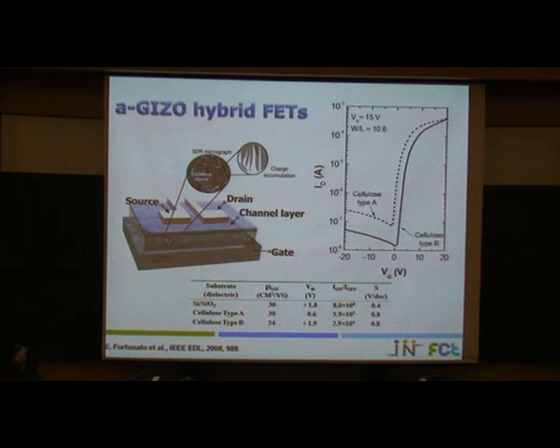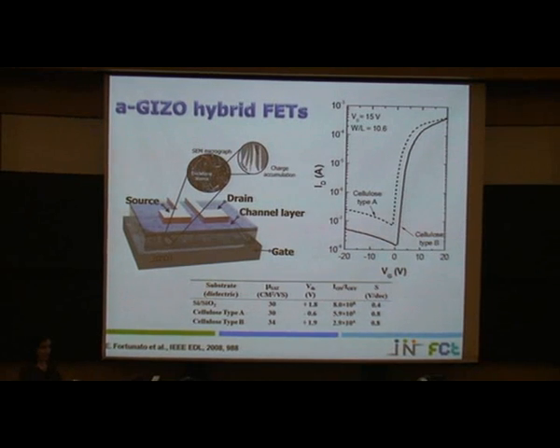And more recently, just to finish the talk, since we are working at room temperature, we are not limited by the type of substrate we are using. We thought to substitute our dielectric film, our silicon oxide or aluminum oxide, with a simple sheet of paper, because you know paper is insulating. And instead of growing all the layers and producing the device with a substrate configuration, layer by layer, we make what we call an interstrate structure, because it's not a substrate, it's not a superstrate structure, it's an interstrate structure, because we start the device from the middle,